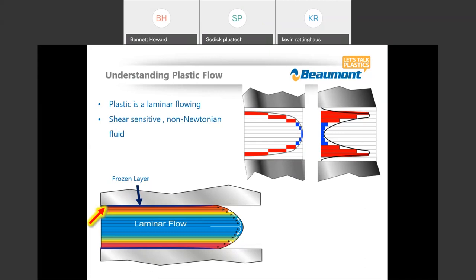The other cool thing about plastic is that it's very shear sensitive. It's a non-Newtonian material, so its shear rate is going to dramatically influence its viscosity. At elevated shear rates, things become less viscous and easier to flow. So the important part about these two factors is that we end up forming distinctly different laminates.